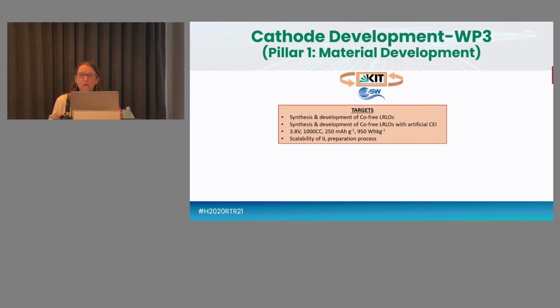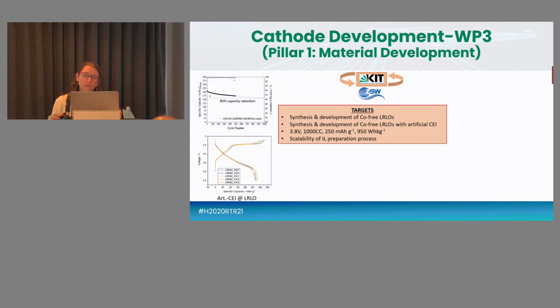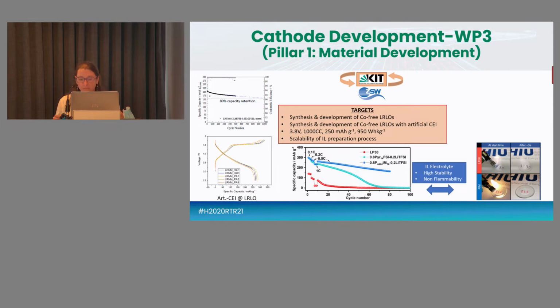Regarding the cathode development within work package 3, this part is led by KIT. At the moment, we achieved 80% capacity retention after 500 cycles with the most promising formulation of the ionic liquid. Because of the nickel content of the cathode, we are also working on an artificial CEI, trying to have better control on the cathode side.